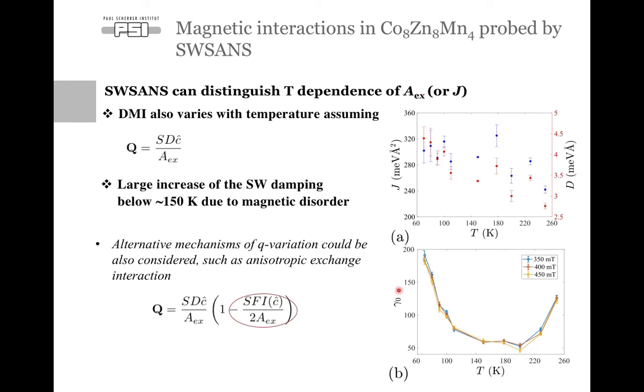However, one can also think of alternative mechanisms that may explain the Q vector change as a function of temperature. Maybe in addition to the thermal variation of exchange and the Dzyaloshinskii-Moriya interaction, one can also think of the so-called anisotropic exchange interaction that is a higher order term in this formula, but it also can affect the periodicity of the magnetic spiral. And that would be a subject of our next studies using X-ray and neutron scatterings.